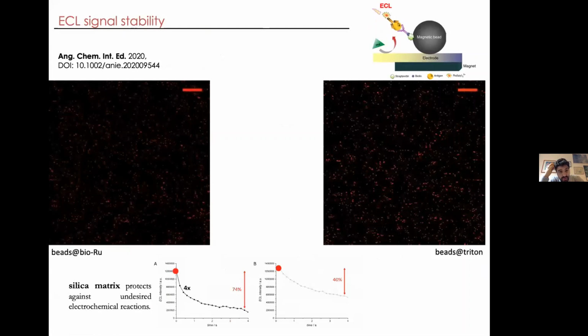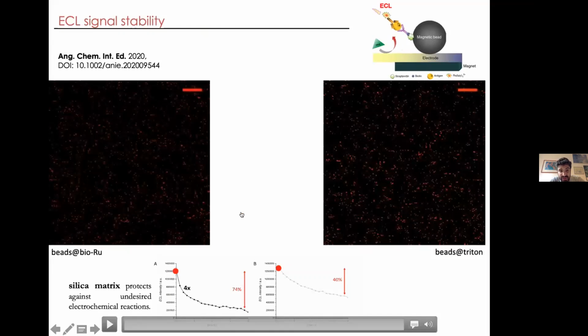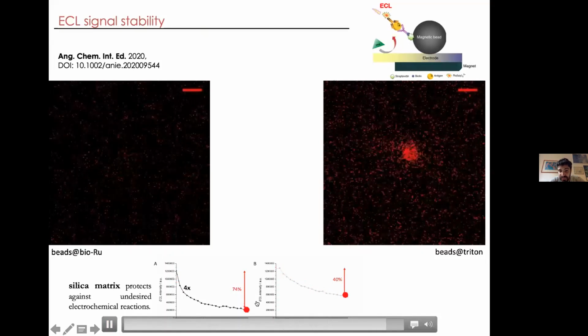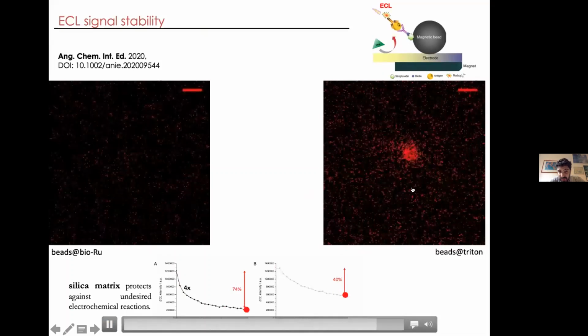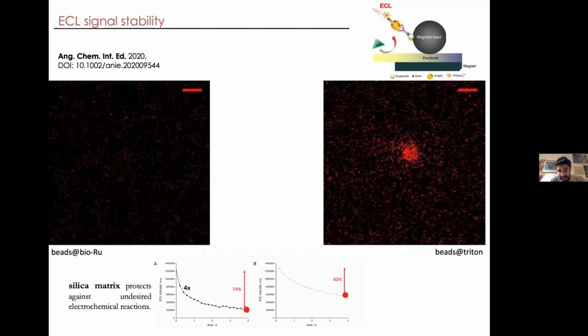One of the main issues in ECL is the stability of the dye over time. So when we have the beads on the electrode and we apply the potential, we typically observe, and here you can see from the movie, this is just a ruthenium one, a decay of the emission and the deactivation of the dye. In the case of nanoparticle, here you see the movie on the nanoparticle, here you see the movie only related to ruthenium tris-bipyridine. And in the case of nanoparticle, the decay is much slower compared with the standard dye. This is amazing, and I thank the reviewer, because we obtained these results by replying to the reviewer.